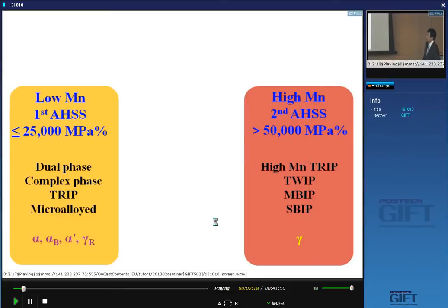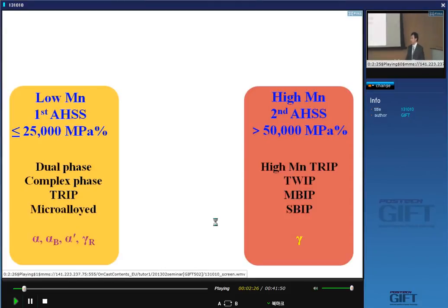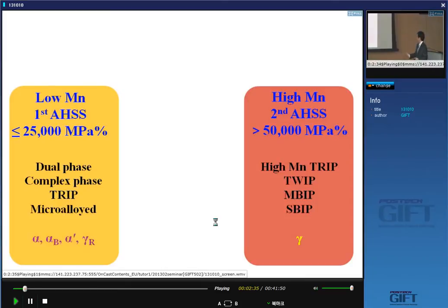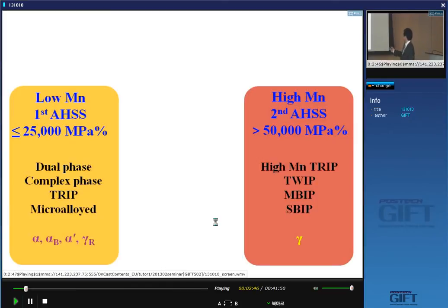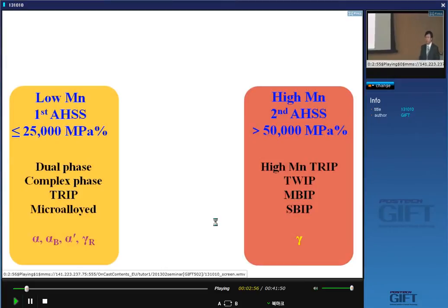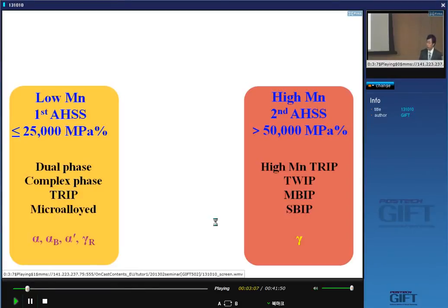For the past decade, many researchers tried to find a new way to improve both tensile strength and ductility simultaneously. The new idea is to use the FCC crystal structure — the austenite structure — but this time not high-temperature austenite, low-temperature austenite. This includes TWIP steel, high-manganese TRIP steel, and deformation band steels. In order to get stable or metastable austenite at room temperature under one atmosphere, that's why we add a high level of manganese concentration. Considering cost and stacking fault energy, we selected manganese over nickel or copper.